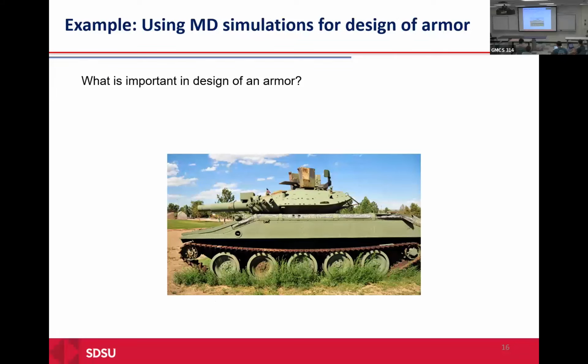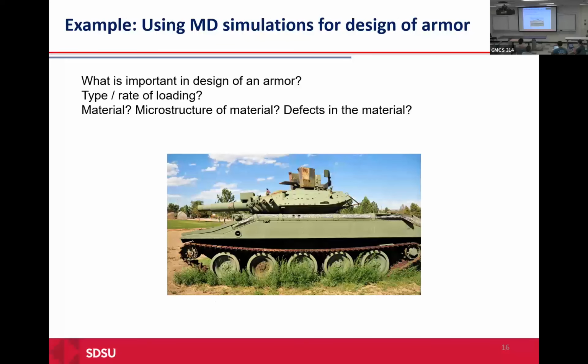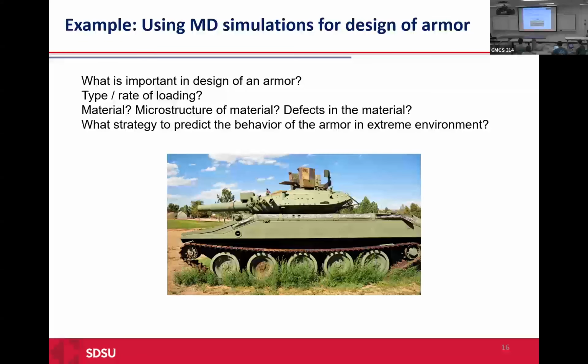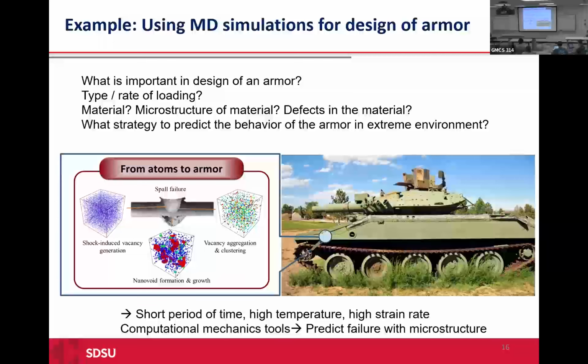Since it's an armor, we are dealing with the highest strain rate type of loading and impact, or different rates of loading. Then the material and the microstructure of the material are really important. The defects that we are generating in the material are important. One strategy is to look at the microstructure and see what is happening when we are dealing with the highest strain rate of loading, for example the impact happening for armor or different defense applications. As I have mentioned, we are trying to use MD simulation, the proper MD simulation, to predict the failure mechanism that is happening during spall.